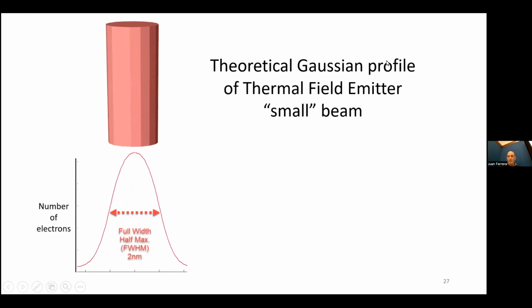So the beam we use to expose with, I did my best with graphics, but not very well. And this is meant to be a 2 nanometer diameter beam. And that beam is not really this columnar-like thing that I'm showing up here. It's a Gaussian beam. So the full width at half max is nominally 2 nanometers, but you have to remember that these tails that are coming out here are going to overlap, and due to other effects like proximity effect, that means we don't have the kind of beautiful, sharp on versus off that you might think you have.